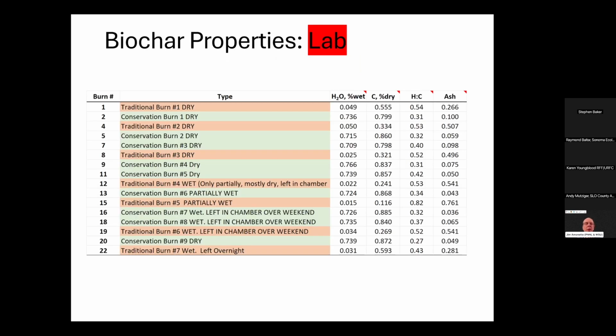Again, we collected the same set of biochar properties. We had 22 burns. You can see we're only reporting the traditional and the conservation burns here. So instead of 22, we have about 2/3 as many, so maybe about 15 or so again, but just for traditional and conservation burn. As mentioned before, we had problems with the kiln. The kiln just did not work in the chamber that we had at the fire lab.